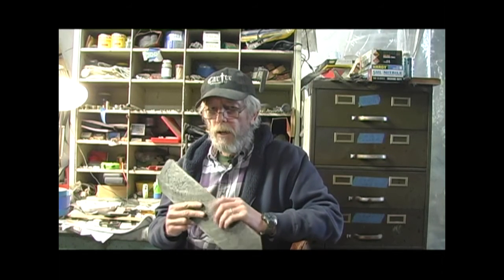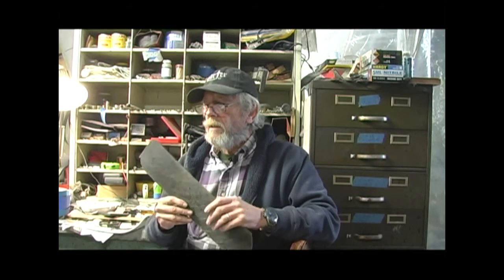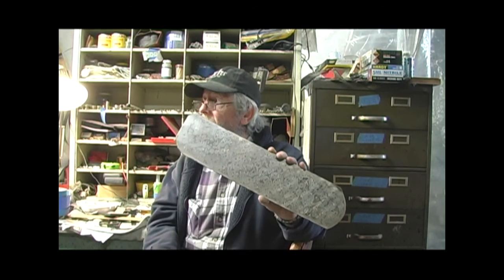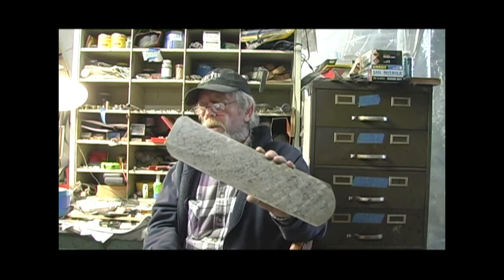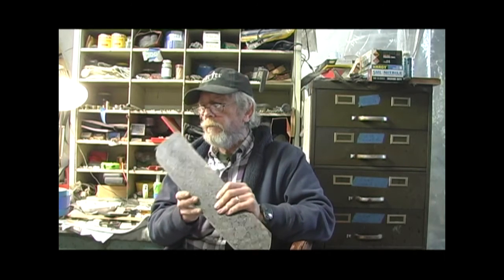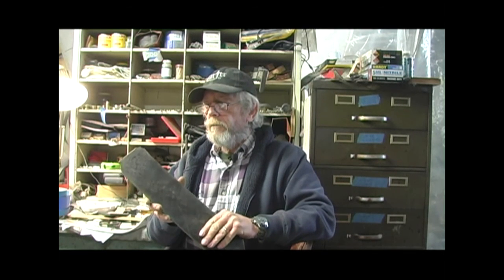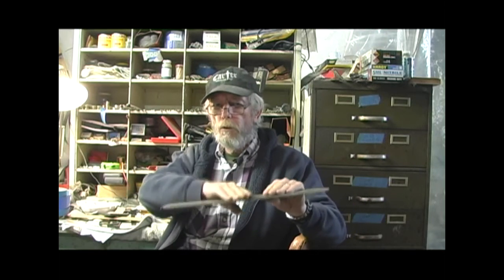I usually use Alabama Damascus, made by Brad Weiss of Alabama Damascus. For example, this piece is 416 layers of 4 types of metal. In this case, he starts with 4 layers of 5160 spring steel, 3 layers of 52100 ball bearing steel, 3 layers of 15N20 bandsaw blade steel, and then adds a nickel alloy to give it some contrast. He takes those 13 layers, they're forge welded together. So you have this solid piece, 13 layers of 4 types of metal. Then it's folded 5 times. It's hammered out, drawn out, folded over on itself.